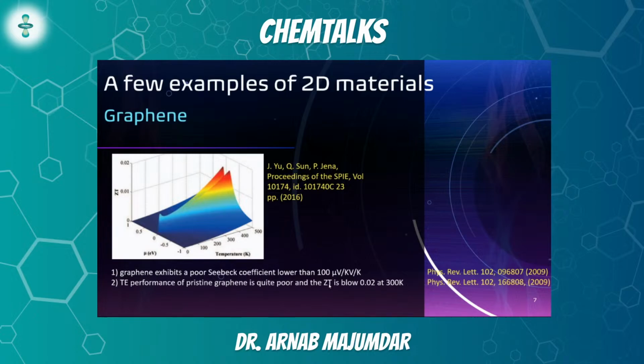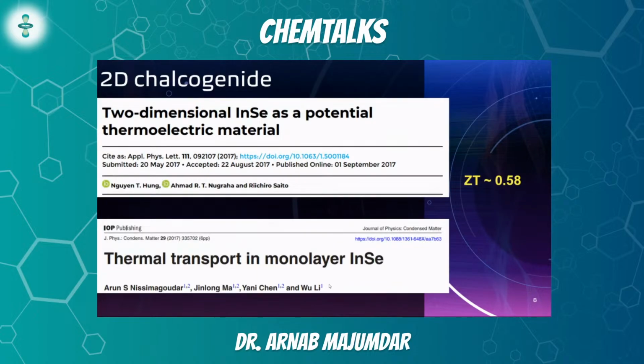But unfortunately, graphene has a very high thermal conductivity and a very low Seebeck coefficient, because of which the ZT turned out to be quite low, in fact lesser than 0.02 at room temperature. So it was not something great. People moved on, and eventually they came up with this other family of materials, the 2D chalcogenides. Here I've just given the example of 2D indium selenide as a potential thermoelectric material. Many different materials have been studied, like Bi2Te3, Bi2Se3, indium sulfide, gallium sulfide, whatnot. And they saw that, at least theoretically, they were able to predict ZT values which were much higher than that of graphene, by the way.